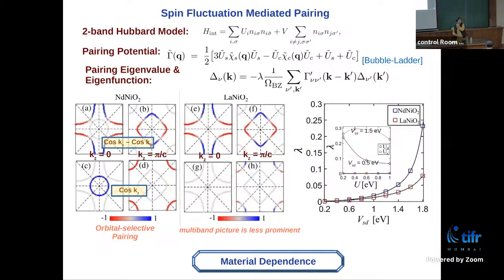And since it has a k dependence, from there you can also talk about the symmetry of your superconductivity. What we find in the neodymium case is basically a two-channel superconductor, where there is x square minus y square like a cuprate, but there is an additional channel contributed by the axial orbital, which is gapless. And there is an STM experiment which agrees with our viewpoint of two-gap superconductivity, one being x square minus y square type, another being gapless. For lanthanum nickelate, in this other channel there is absolutely nothing, because the axial orbital I showed you has a very small electron pocket that's almost disappearing.